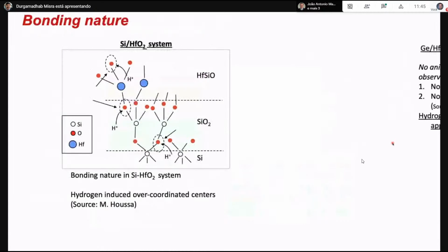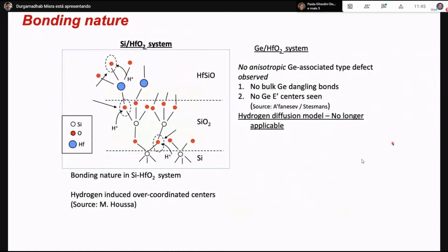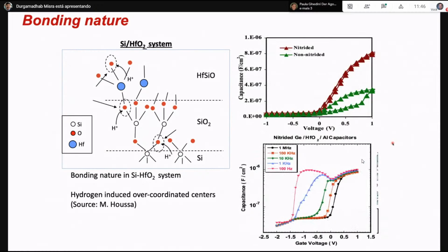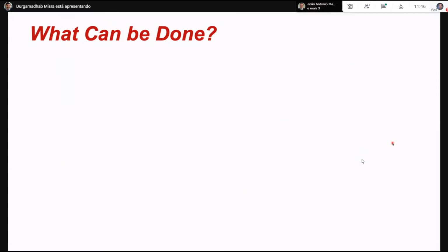The interesting part is that it is different compared to the silicon dioxide interfacial layer, because the germanium system has no germanium dangling bonds in the energy gap of germanium. They are actually in the valence band, below the valence band. So this creates problems in detecting the dangling bonds of germanium. When we did the nitrogen passivation, the hysteresis went down, but it showed a lot of frequency dispersion. So the passivation was not a solution. So what can be done?